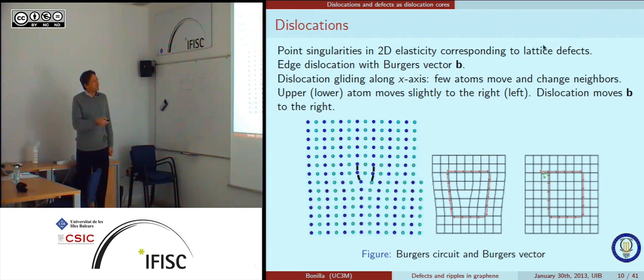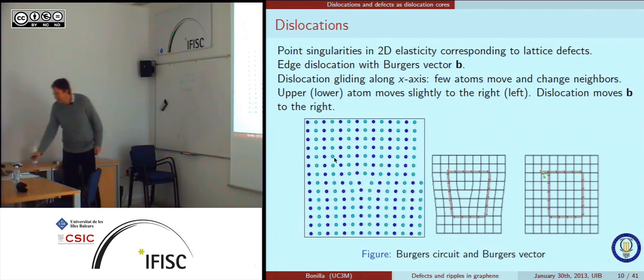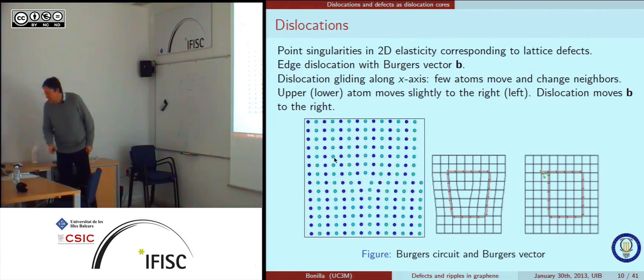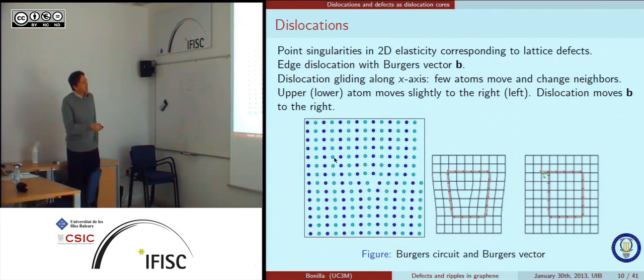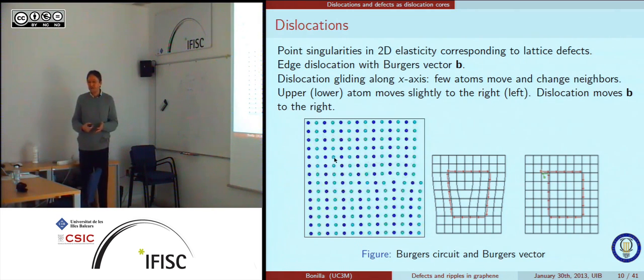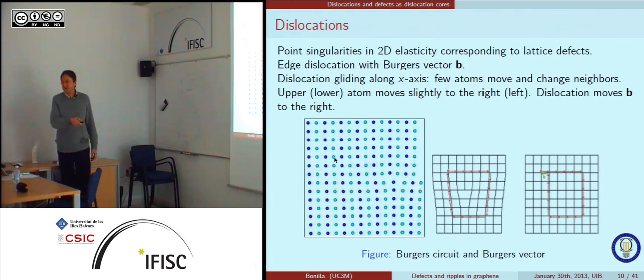If you push here, you shear the sample, so you put a force that points to the positive x here and negative x there. What happens is this. You see the very small motion of the atoms here, and you perceive that as a motion of the whole dislocation. So this one is going to move, and that means the dislocation that started there is now over there. That's how dislocations move. A very small motion of different atoms gives you a large displacement of the defect.